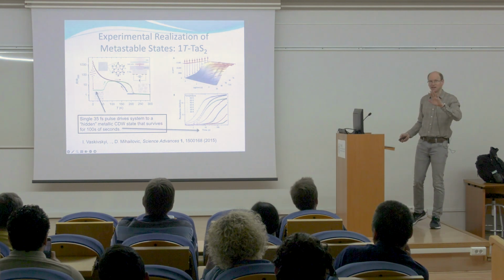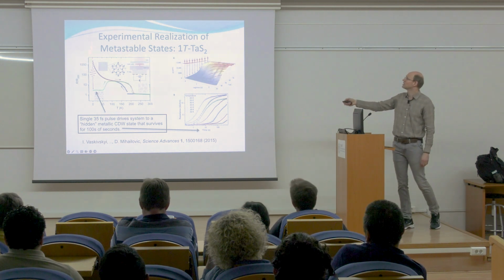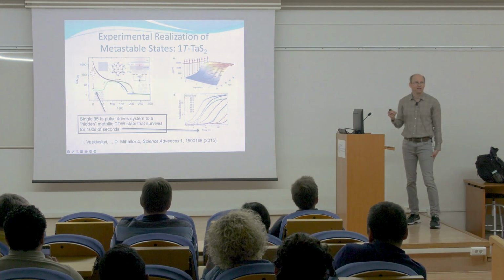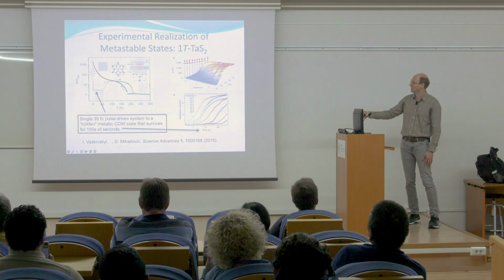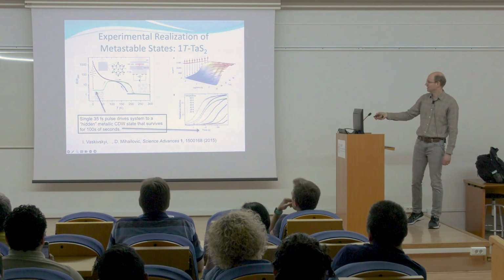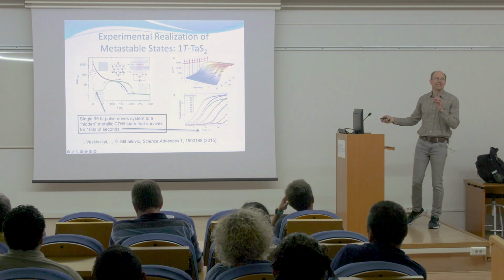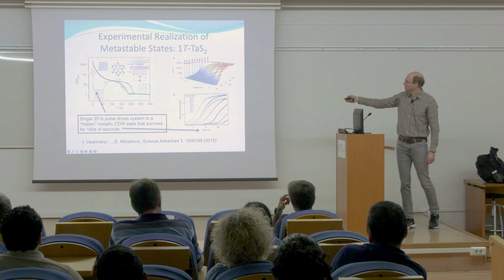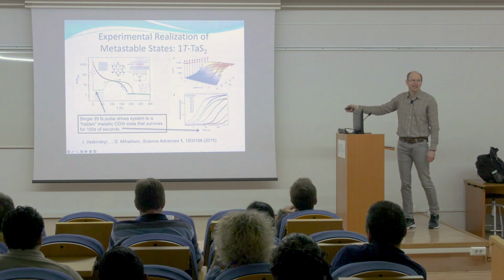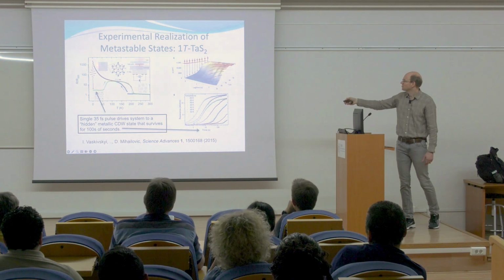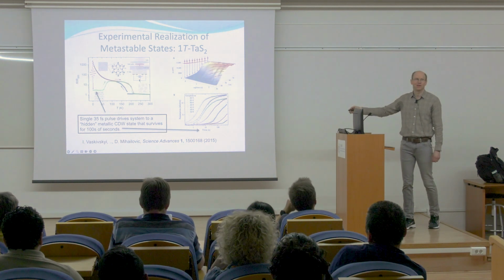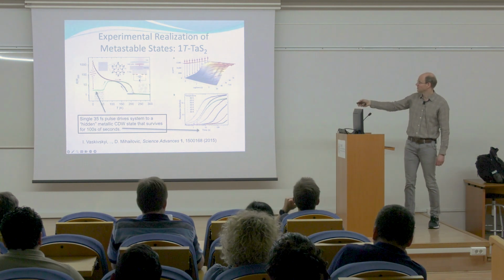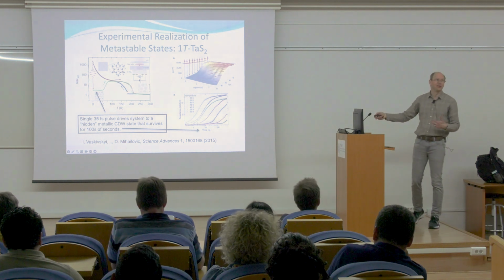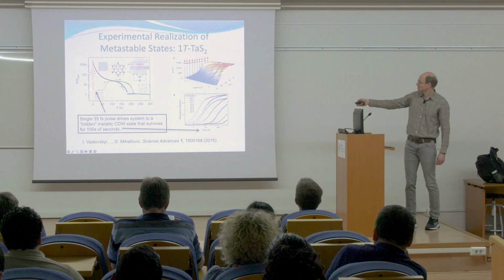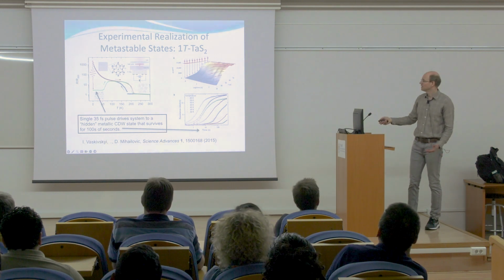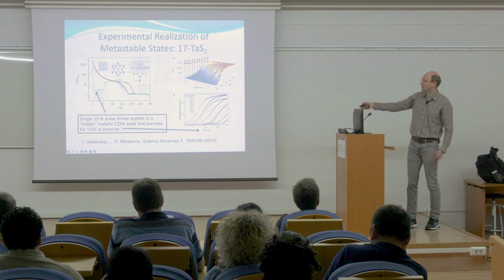So this is a very good insulator because its resistance is increasing very rapidly as you go down towards zero temperature. However, if you hit it with a single pulse of light, 35 femtoseconds in length, and of a certain intensity, then the resistance abruptly drops from a very resistive state to a metallic state, and simultaneously the charge order changes to a different symmetry type, which is different than something observed at high temperature. So you induce a kind of hidden charge order in the system, and this hidden charge order will persist for some amount of time. And the lower the temperature when it's hit with the light, the longer it will persist.